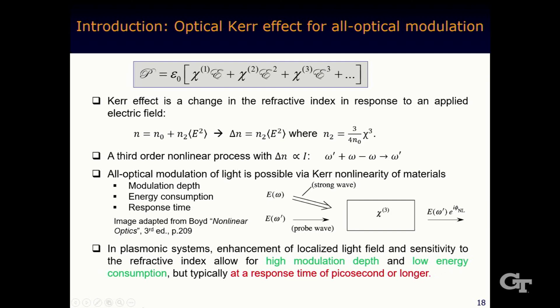There are many important results from this third order nonlinear optical process. One of the most important ones is the optical Kerr effect. The optical Kerr effect can be viewed as a frequency mixing behavior without changing the frequency, because omega plus omega minus omega is still omega. But this gives rise to a direct consequence: the refractive index is sensitive to the electric field magnitude squared, or the intensity of light. So the intensity sensitive refractive index. And there are a lot of major consequences from this optical Kerr effect. If only one beam is involved, the optical Kerr effect can lead to self-focusing, self-phase modulation or modulation instability.